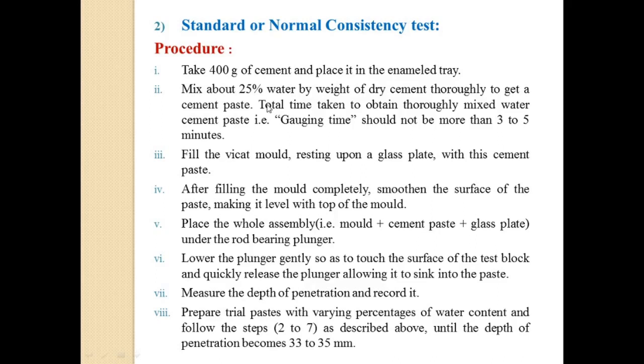Then we release the plunger into this cement paste. It may go down below the 33 to 35 mm. Firstly, suppose it goes down to 40 mm, which means the water content is more in that cement paste. So in the next trial we reduce the water. Suppose we take 23% of water by weight of cement. Then we repeat this whole procedure again.